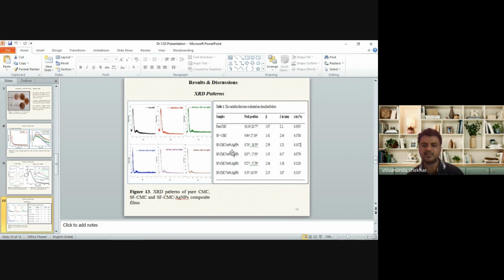So we confirm with a different 2 theta angle, and also we have calculated the crystallite size and also the lattice strain. So here the silver nanoparticles are immobilized in the composite matrix. We have done supporting evidence along with transmission electron microscopy. We get to know the formation of silver nanoparticles in the composite materials.